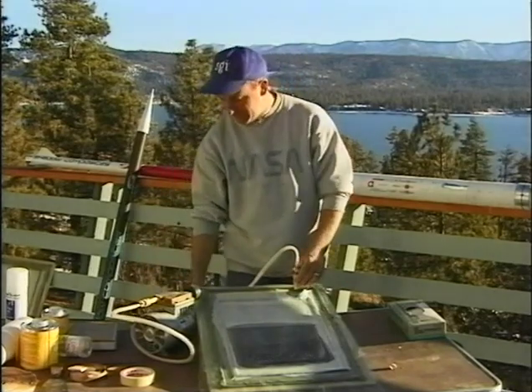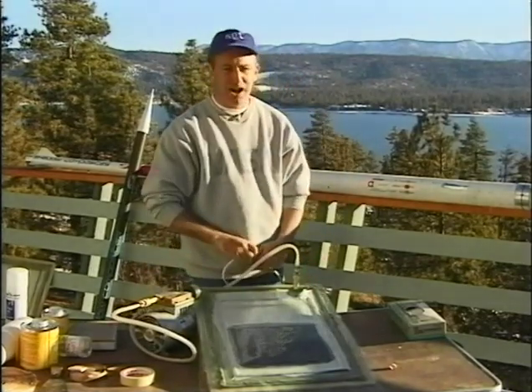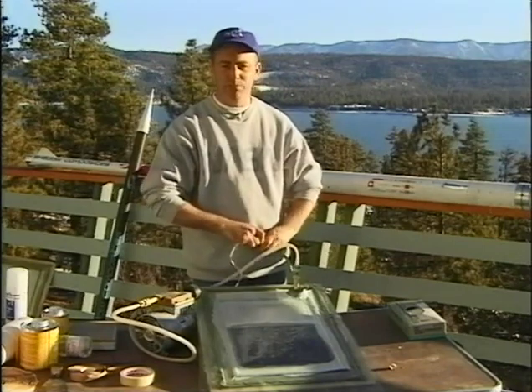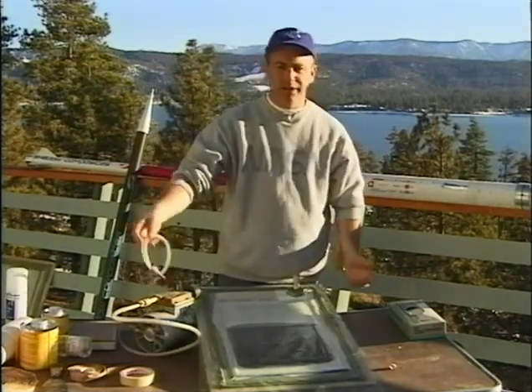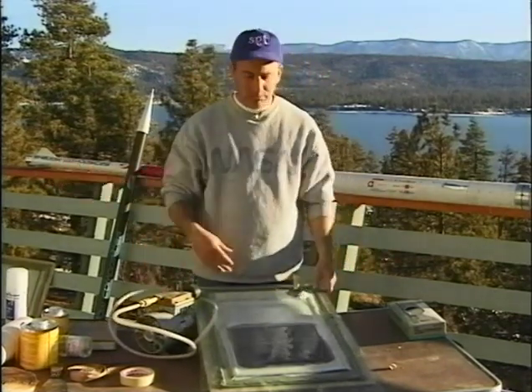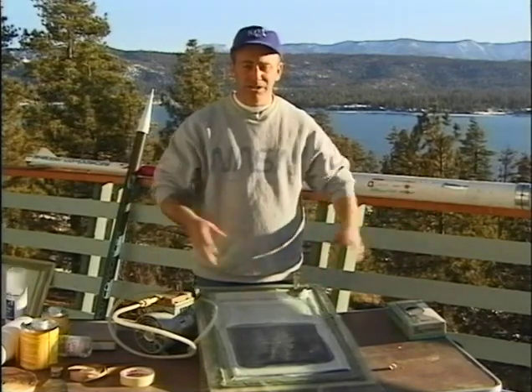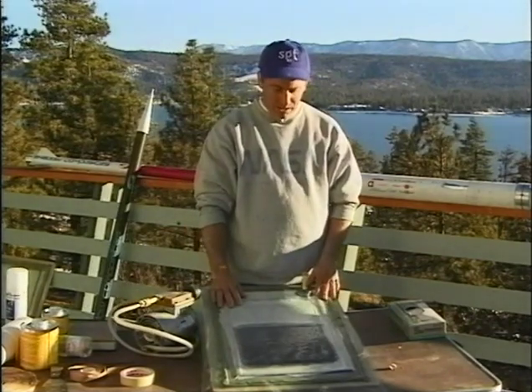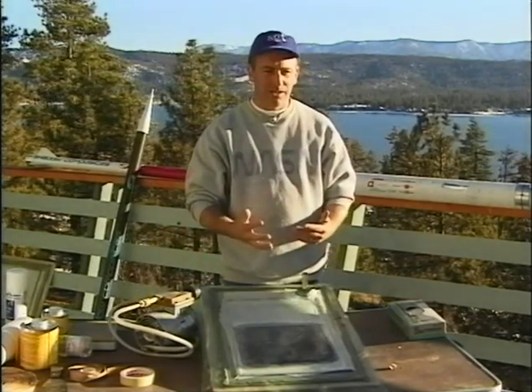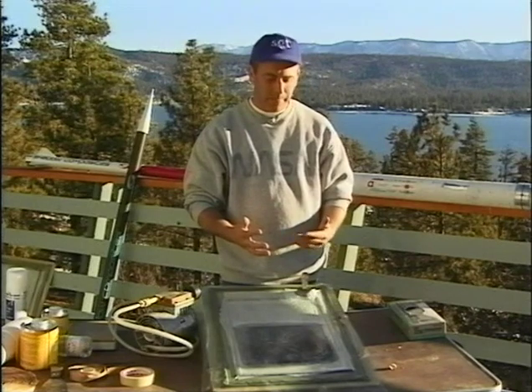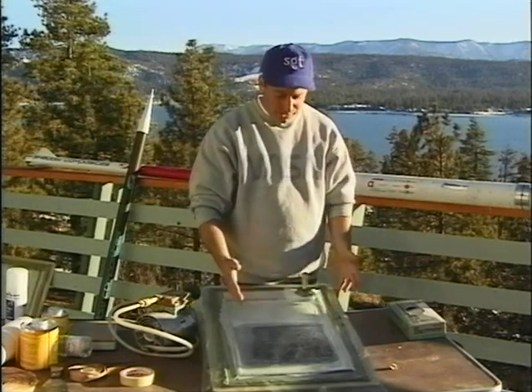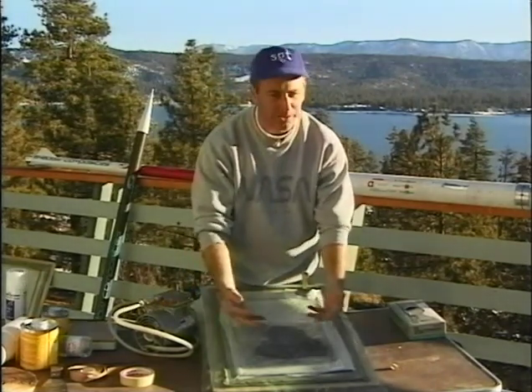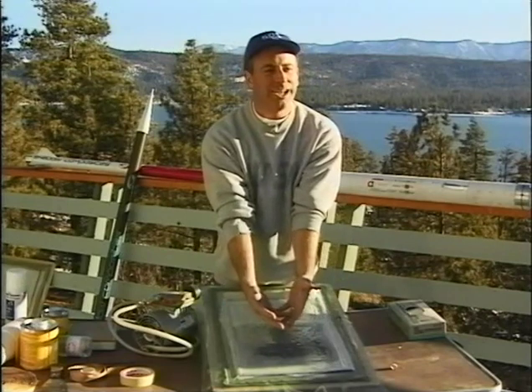It's very tempting for some people who are doing vacuum bagging for the first time to at this point say, well, I'm vacuum bagged, shut off their pump, pull the hose, and go put it in an oven or whatever, you know, just let it sit. What's going to happen if you put this in an oven right now, there is a little bit of outgassing from the epoxy resin as it cures. What it's going to do, or if you just let it sit, if you look in here, looks like ice crystals coming in. That's air coming back in to the bleeder breather layer.